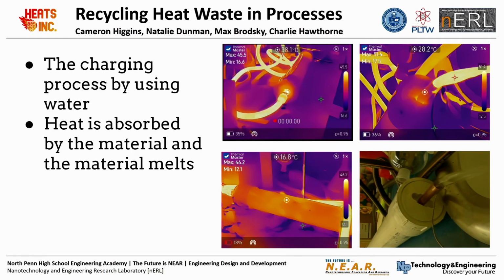To charge the thermal battery, we ran a hose through one end of the copper tube and then ran water through it into the battery. As the hot water ran through the battery, some of the PCM inside absorbs that heat. And as the PCM reaches its maximum energy capacity, it begins to melt.